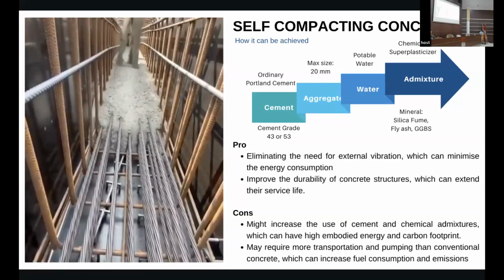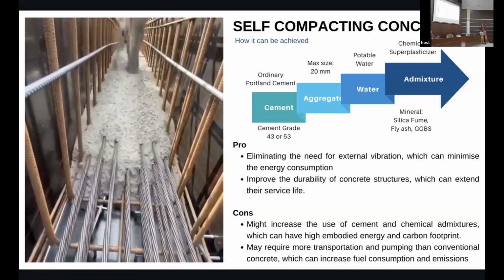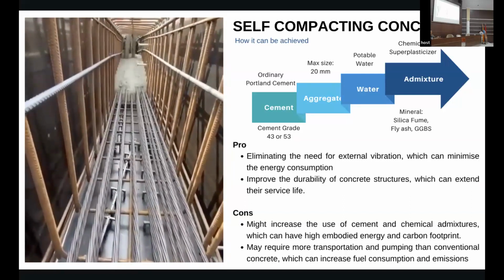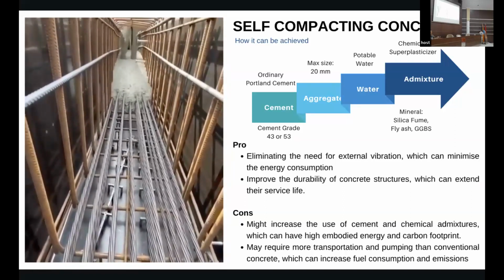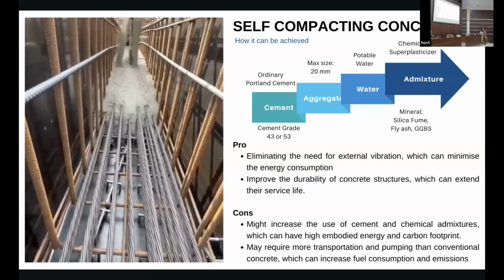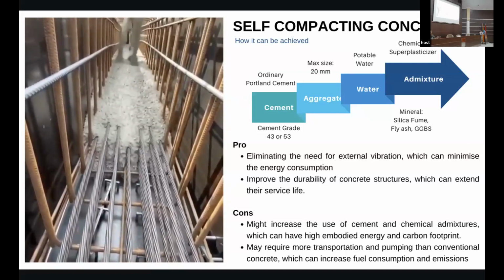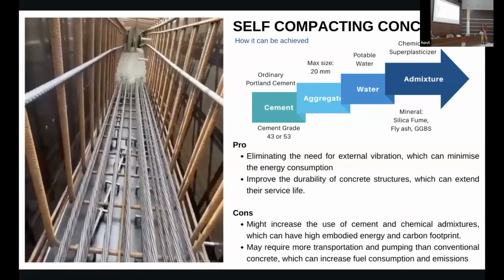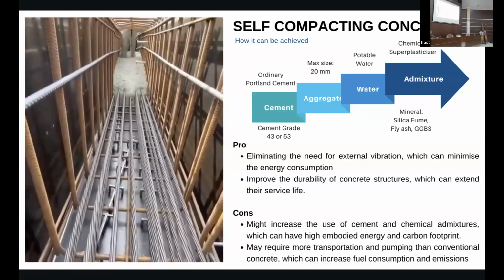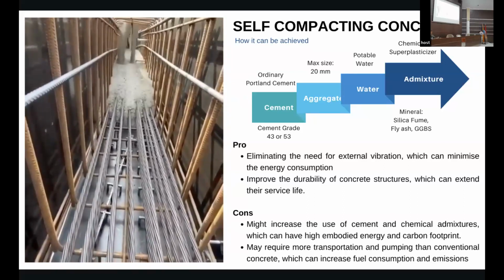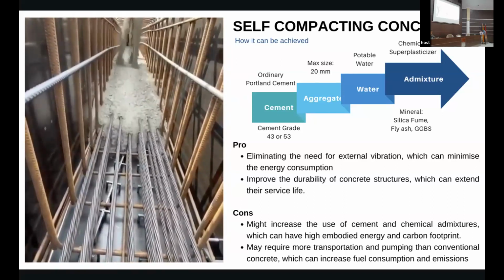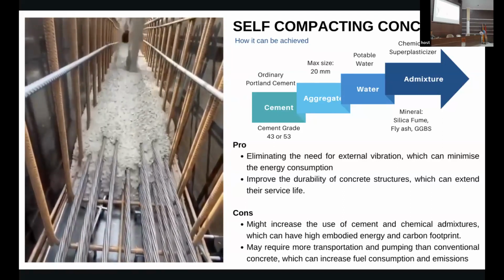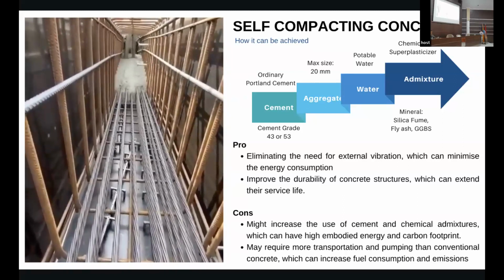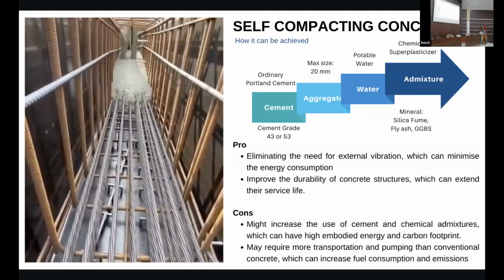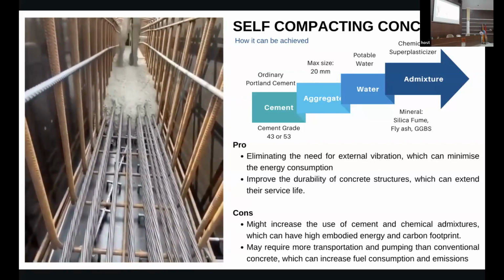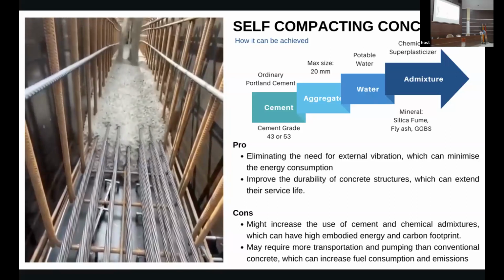The components are similar. You still need cement, maybe grade 43 or 53. And then you still need to have the aggregate, but not too big. Maximum is about 20 millimeter. And you still need water. What kind of water? The potable one. All the water that you can drink is safe enough for the concrete. And admixture. The admixture is the one that makes the SCC different from ordinary concrete, the normal concrete. So the SCC in here has two normally, the chemical and mineral. Mineral admixture is needed to achieve the higher strength. Right. The chemical admixture is needed to increase the flowability of the concrete.